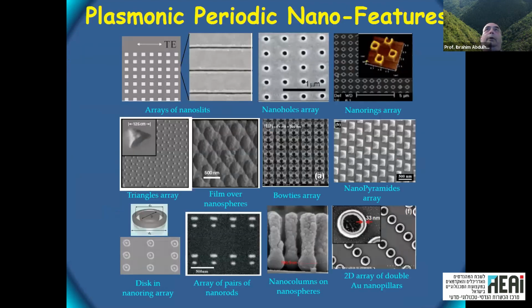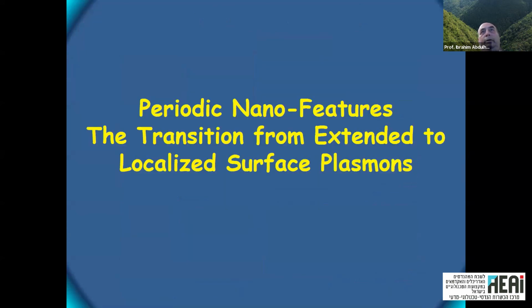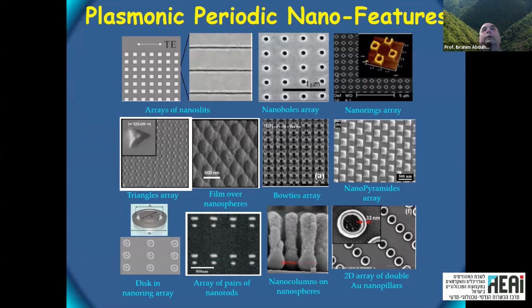Okay, before we go to nanoplasmonics, we would like to do something called a transition from extended to localized, from plasmonics to nanoplasmonics, let's say. And we do that by having a periodic structure. Why? A periodic structure is like a grating. It gives you extended plasmon, but on the tip of the grating, on the edge of the lines, or could be on the edge of a prism, it can give you localized plasmons, right? So it's a kind of transition between the two regimes.